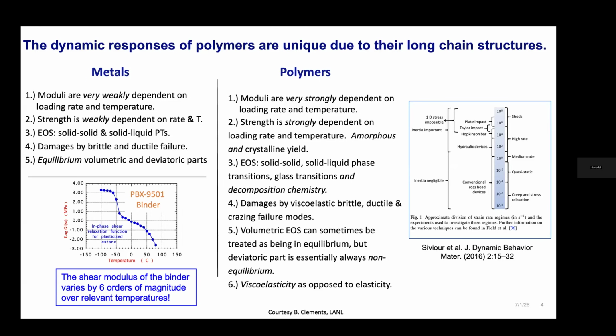If you look at their damage responses, they damage by different mechanisms than metals. They damage by a number of different mechanisms: viscoelastic, brittle, ductile, and crazing failure modes. That's something I'll talk about at the end that we're trying to get real-time data on as far as failure. And then as far as the EOS development, we could potentially treat a lot of materials as being in equilibrium in terms of their EOS. But when we are developing equations of state, particularly at these lower rates, we incorporate a deviatoric component, which is basically always in non-equilibrium, and that deviatoric component is based on viscoelasticity. So I just wanted to point out some of those differences in a single slide.